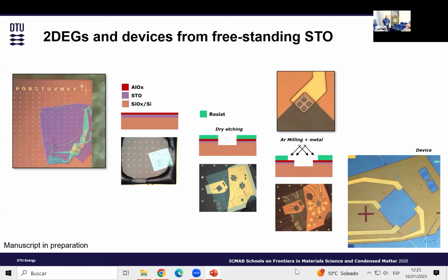And the way that we did it is because we used to work before with Jeremy Levy, and he did the same basically. He or many other people did it also, but we did it for the 2DEG. So you can argon mill it, and then you metallize the material here, so you get a contact into the 2DEG if you put metal all the way. And this is what we did. So what you see here is the contact, and you have four metallizations, at each point, in order to make sure that we're getting contact to the 2DEG. So we did it, and this is one of the devices that you can see.